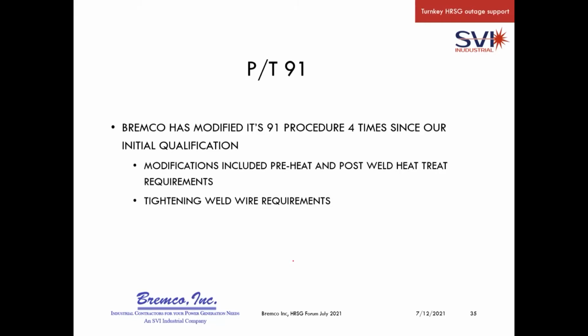the information has evolved into the type of repairs that need to be done and the research that NBIC and ASME and EPRI have spent a lot of time with, and it involves tightening of the specs. When we first started looking at 91, it was considered a P1 material, so essentially anyone could weld it. Anyone that was a qualified welder, P1 to P1. It's obviously since evolved into highly technical welding requirements with very tight pre and post weld requirements. It's also one of the other things that we found is the weld wire requirements have tightened significantly since we've begun welding on 91.